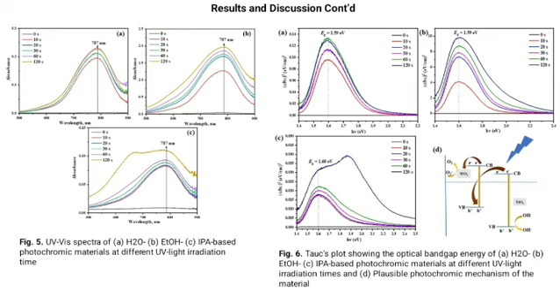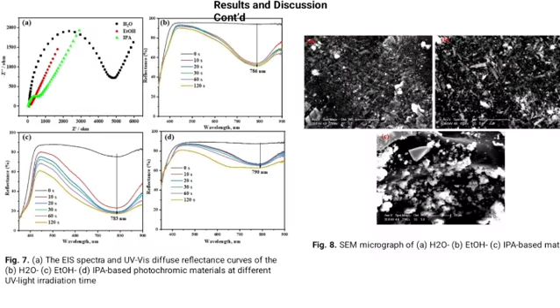However, the efficient promotion of electrons from the highest occupied molecular orbital to the conduction band will trigger a high sensitivity of the charge transfer complex in the visible region of the spectra, thereby producing the photogenerated oxygen radicals for color development. Moreover, the electrochemical impedance spectra of the material displayed a higher conductivity in the water-based compound due to the presence of dispersed inorganic ions in the material that can interact with the ionizable molecules.